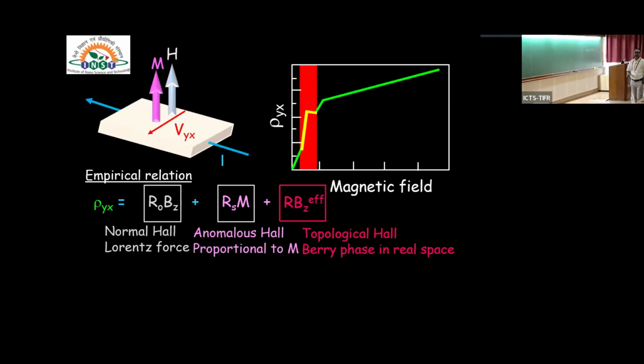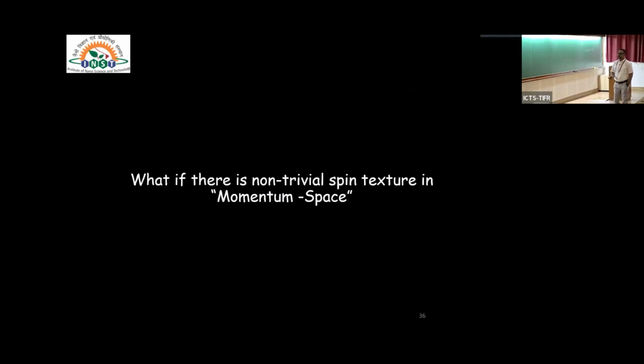But if you have a system with a non-trivial magnetic spin texture, then in addition to these two you see another term coming from the Berry phase idea, giving rise to something called B effective. This is a pseudo-magnetic field, and it gives rise to something very weird in the system, known as the topological Hall effect, coming from the Berry phase in real space. But here you are looking not at the longitudinal resistance but at the transverse resistance under the application of a magnetic field, which is the normal Hall. But what if there is a non-trivial spin texture in momentum space instead of real space?